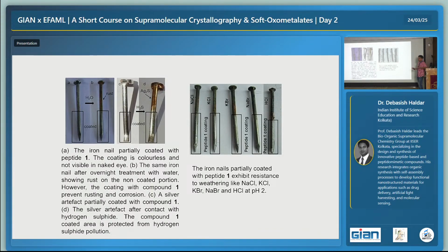So without any very difficult processing, just coat with this material. It is completely colorless, you cannot differentiate between them, and you can protect it from rust formation. Not only that, this is a silver artifact. We know that if you use silver ornaments for a few days, and there is hydrogen sulfide, the silver will react with hydrogen sulfide and turn black after a few days.